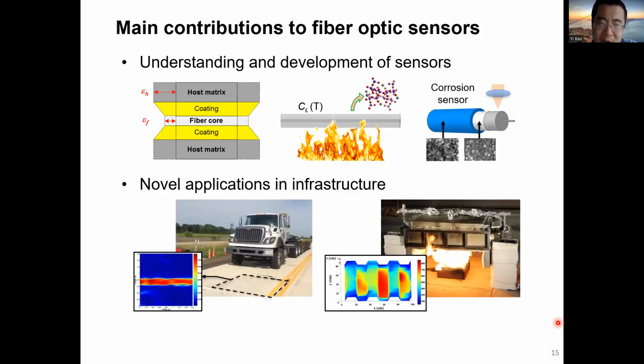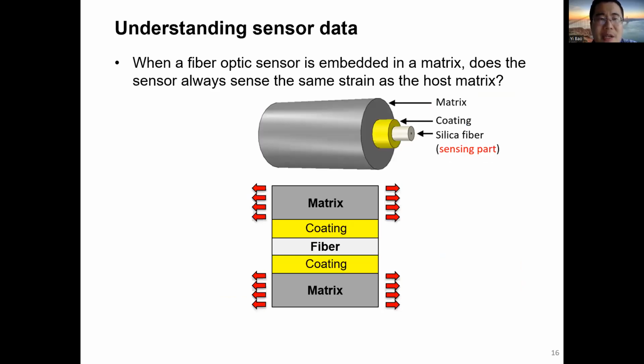We also applied those sensing technologies for civil infrastructure, including normal temperature applications and high temperature applications. So first, if we want to use the fiber optic sensor to measure strain, for example, strain in concrete, we can embed the sensor inside the concrete during concrete casting. Then after the concrete is hardened, we can measure the strain change, right? But if you recall, in a previous slide I showed that the fiber optic sensor has a protective coating. For example, we use polymer coating to protect the optical fiber, because the sensing part is the glass fiber. The glass is fragile, right? We have to use some materials to protect the fragile glass.